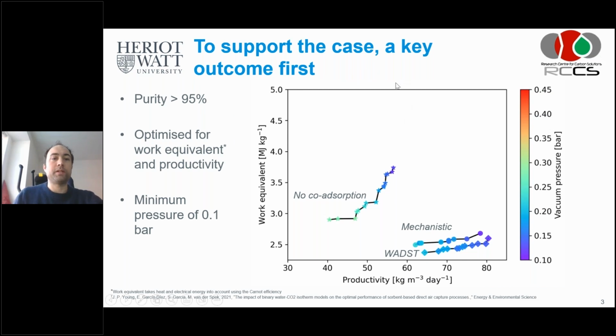And what I'm showing here is some modeling that we have done for a direct air capture process. And what you see here is two key performance indicators. On the horizontal axis, we show the productivity, so basically, how much CO2 can you capture per cubic meter of adsorbent bed per day? And then on the vertical axis, we show the work equivalent. That's a measure of the amount of energy, but all fed back to second law work, that you need to achieve that. And what you see here is 3 Pareto fronts.